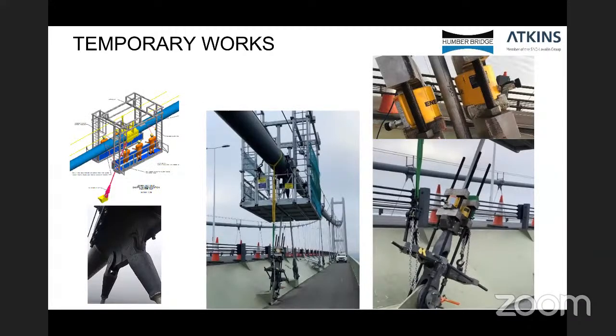So to replace these three hangers, we needed a temporary works design that could safely remove the hangers whilst the bridge was open to traffic. Now, part of the detailed analysis work that we've carried out to date is, can we remove the hangers without closing the bridge and also without putting in temporary works to support the decks? Now, because of the loading distribution of the hangers, it was very critical that during the replacement there wasn't full live loading on the deck, and so for that reason there was a partial closure down to 2 lanes.